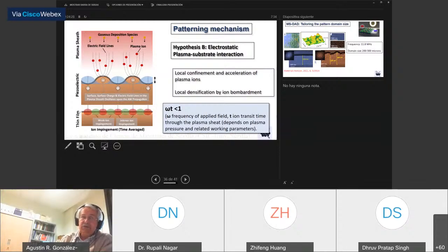So what we have assumed, and we are now modeling, is that in this area where we have a change in the electrical polarization, there is a concentration and acceleration of the ion beams of the plasma, which, impinging on the surface, are producing in this area a considerable compaction, as happens in conventional techniques using ion beams to produce the compaction of the deposited film.